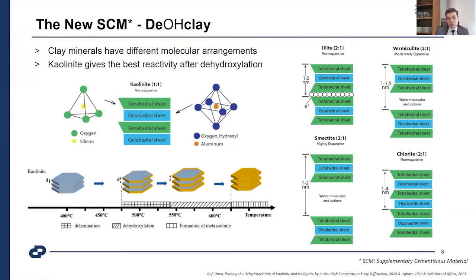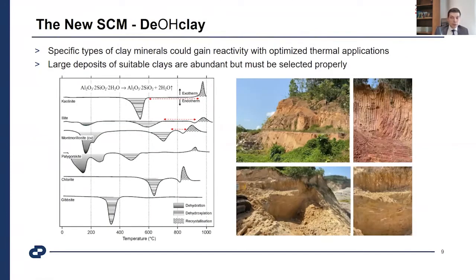But in the calcined clay approach, the aim is not to use specific clays only, but to find achievable and proper clays, mixing kaolinite, illite composites and other things with some specific features, to get a really reactive supplementary cementitious material. At this point, here are some photographs from the field while we were researching clay for the Abidjan plant in Ivory Coast. In Africa, especially West Africa, abundant resources are available over the bedrock, with a high thickness of material available for clays for calcined clay production.